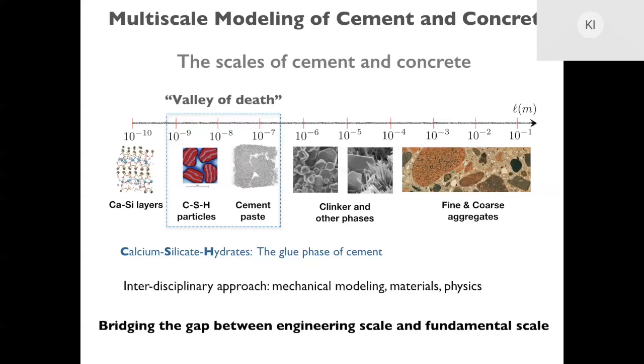In the past years we have done a lot of work to try to connect the atomistic scale that you see on the left with the mesoscale that is in a box in the middle. So basically we have tried to upscale properties from the atomistic scale, the chemistry of calcium silicate hydrates, into a particle-based model through the interaction of these particles, and to understand how this is influencing the texture and the mechanics of cement. In this work, we went one step further, and we also introduced water and ions in the pores of cement to see what is the effect on the mechanics of this porous material.